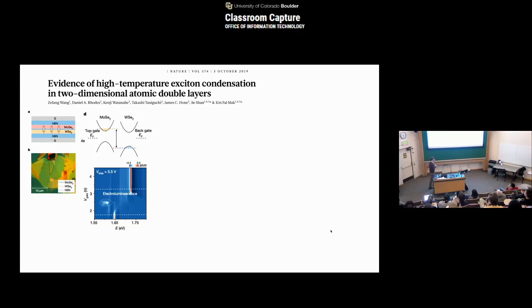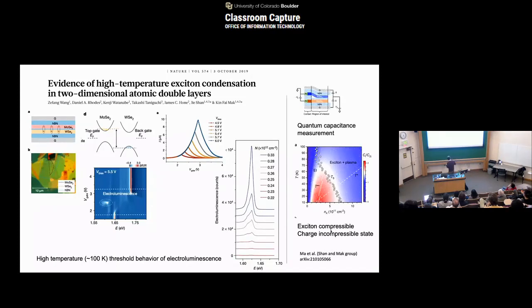By doing so, they have this disadvantage that they don't get light directly coming from the interlayer exciton anymore, because now the lifetime is even longer, and there is a very small opportunity for them to recombine and give us light. But the lifetime becomes quite a bit longer, right? What they see is that they use electrical electron and hole injection and make a tunneling regime. And the tunneling current shows a very strong singular behavior, especially a nice cusp appearing in the tunneling current. It turns out the detailed analysis tells us that the tunneling current is associated with the same amount of electron and hole injection in the system. The sharp cusp in the transport is a good indication that something interesting is going on.